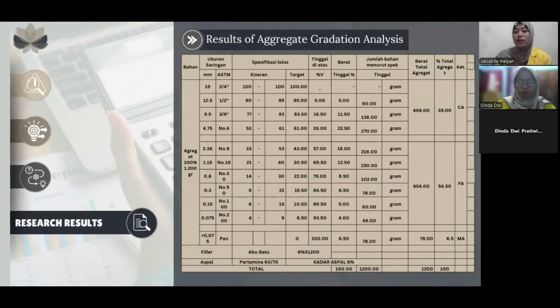The aggregate mix has coarse aggregate 39%, fine aggregate 54.5%, and filler 6.5%. We use 6% asphalt content. This mix is designed to meet asphalt concrete wearing course standard and make good quality asphalt.